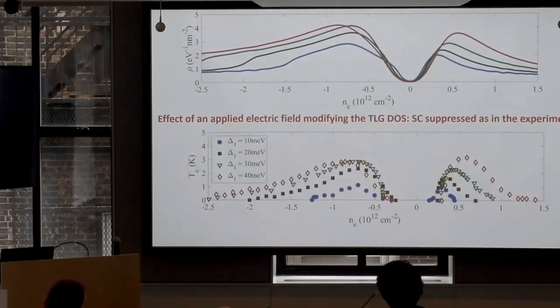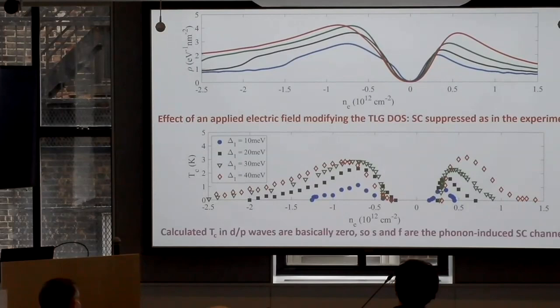And then we calculated how an electric field will modify things. As you know, electric field changes the band structure, and we can calculate it. So these are various gaps that the electric field introduces, and eventually, superconductivity should be suppressed. We did it because experimentalists did it, and it agrees with the experiment. It's suppressed by the electric field.